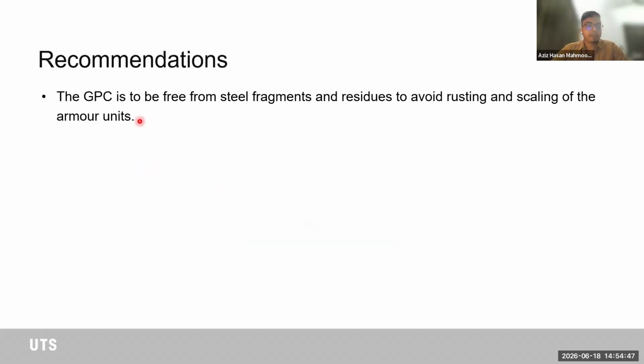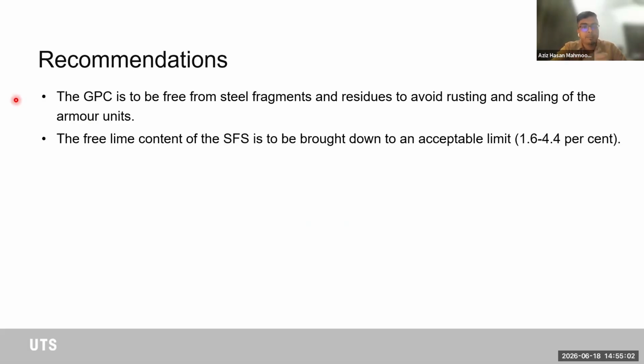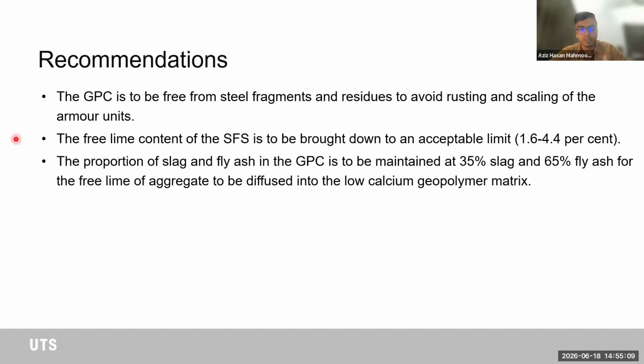But a few recommendations came out of the durability study after 3 years. So we need our geopolymer concrete to be free from steel fragments. The steel fragments come with the aggregates because these are byproducts of steel making industries. The free lime content, we did recommend that it should be within an acceptable limit of 1.6 to 4.4%. The proportion of the slag and fly ash needs to be maintained. So we went for 35% slag and 65% fly ash, and this comes based on 10 different trials, 10 different mix designs of geopolymer concrete mix.